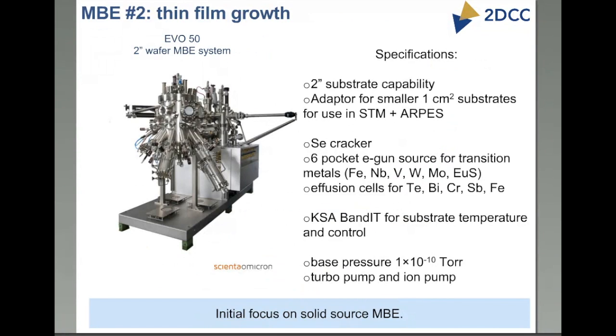Some of the specifications of these systems: the thin film MBE system is going to have a 2-inch wafer MBE. It'll have an adapter for smaller centimeter squared substrates so that we can go into the Scienta Omicron STM and other chambers. It'll have a cracker for the selenium. It'll have an E-gun source, effusion cells, and either a BandIT system for substrate temperature control or an ellipsometer. We still have to decide which one we want to put into place.